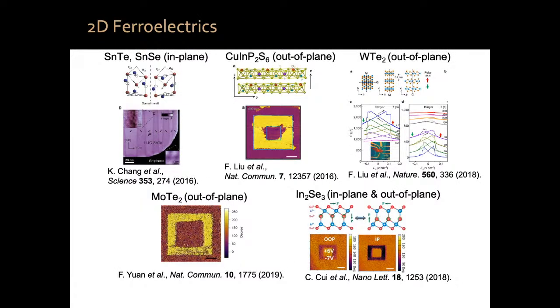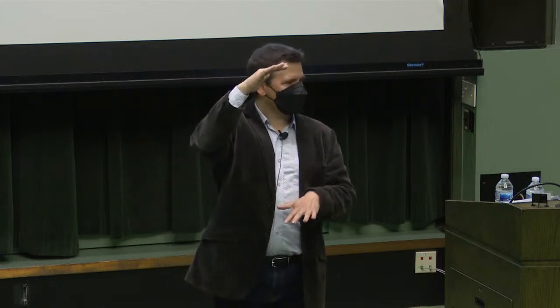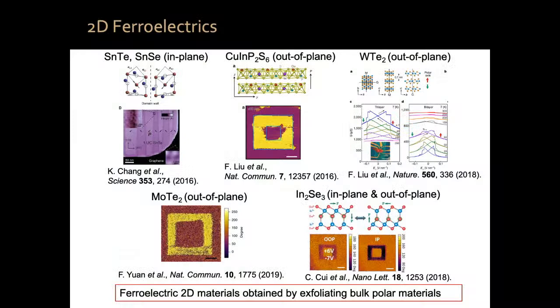And this is something which, in general, in condensed matter physics, orders don't like to exist in 2 dimensions. Okay? There is a famous theorem that forbids you from having ordered states in 2 dimensions, but like most theorems, they don't really work, and we still have order in 2 dimensions. But it's rare. If you take a superconductor and you make it 2D, typically it weakens or disappears. If you take a ferromagnet and you make it 2D, typically it disappears because of fluctuations. So with ferroelectricity, it's similar. There are only a few, I think these are all of them, two-dimensional ferroelectric materials. And these ferroelectric materials essentially all come from exfoliating a bulk material which is ferroelectric.